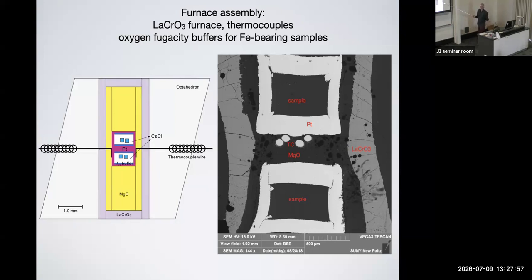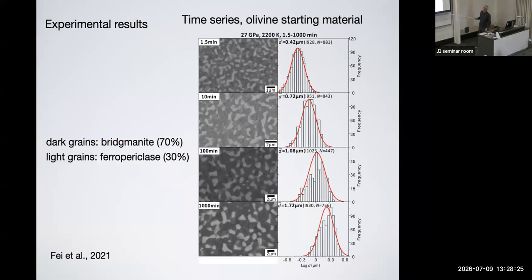The assembly actually looks fairly good, it's not sheared, right? The sample capsules are square. So this is what we like to see, right? So we had near hydrostatic conditions maintained for up to a day at that pressure and temperature. And this is a slightly different assembly. Here are the thermocouple wires, again, showing that we measure the temperature close to our samples, which is important for constraining the temperature. So, experimental results.